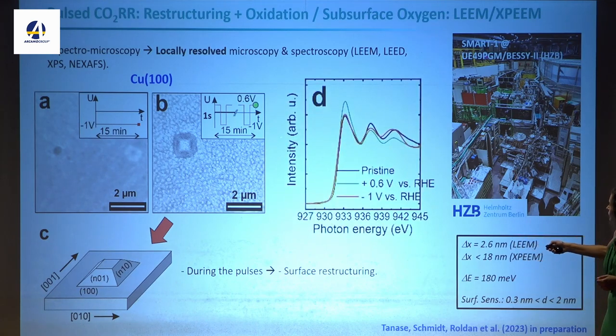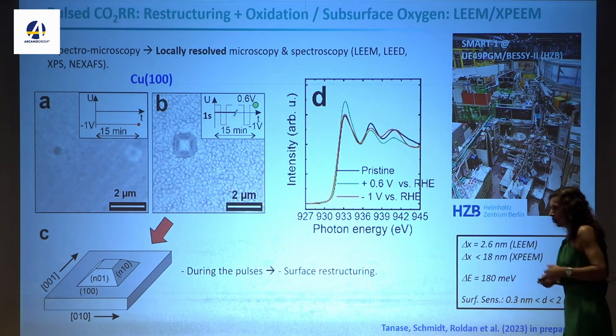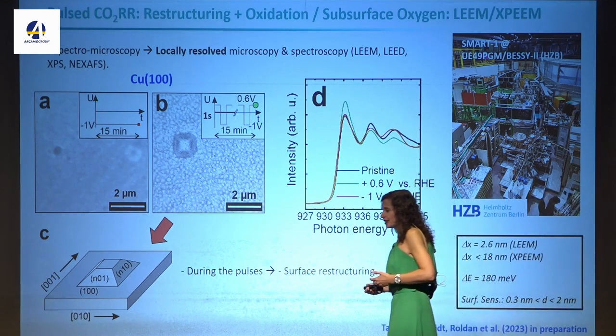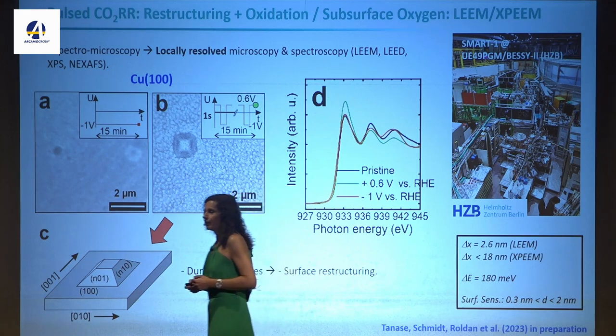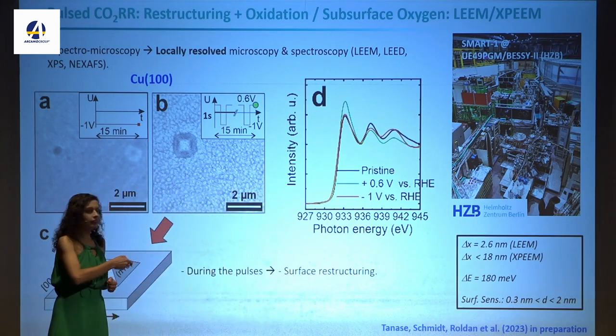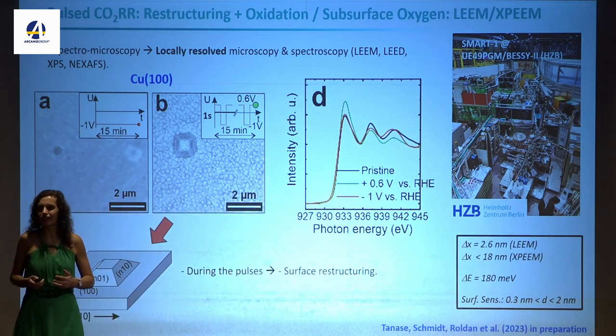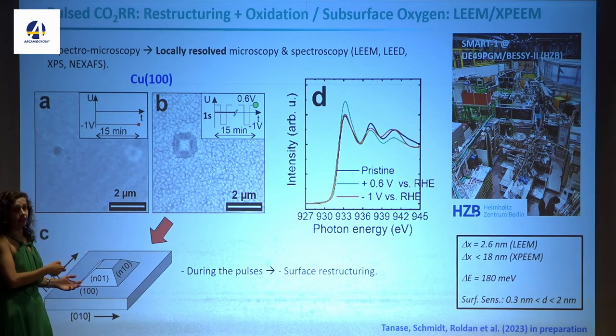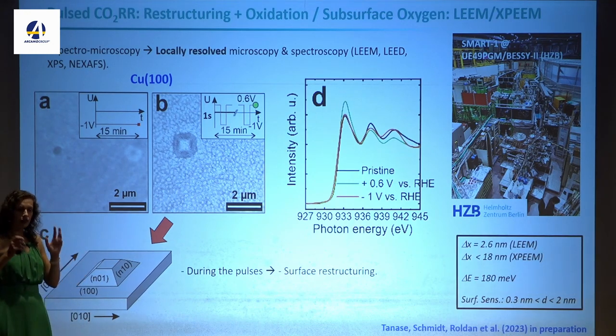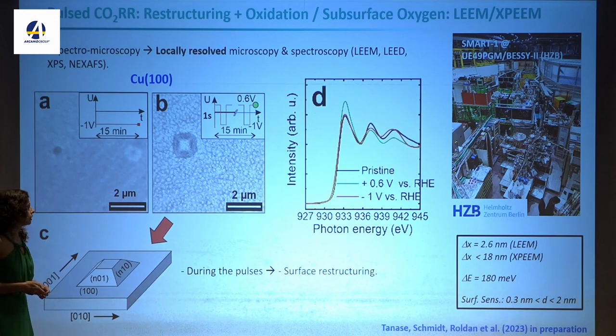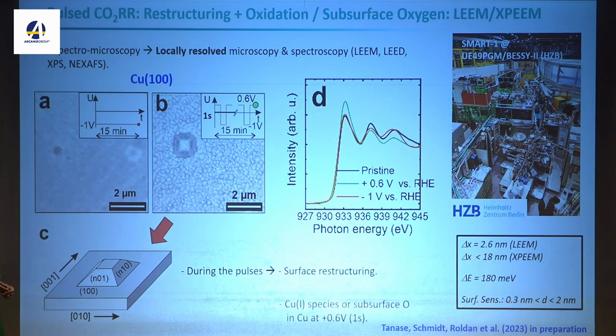So I can do my NEXAFS measurements, and I can see here, if I stop at the positive applied potential, I don't have metallic copper. And if I go to the negative potential, I see the strong reduction, but look at this data here. Always we are trying to explain catalysis based on shifting the D-band level. But what about P and D states? These also play a role, and we can see that things are changing. So if you are working in theory, think a little bit about not just looking at the D state, but look at the others that might also have an important role.